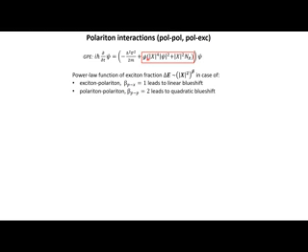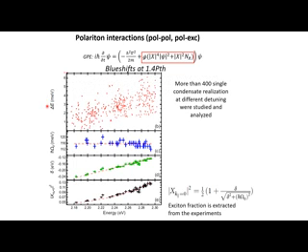So first we investigate polariton interaction. Is there any contribution from polariton scattering or polariton-exciton scattering that we know is present in the standard Gross-Pitaevskii equation for the polariton system? We experimentally studied how the blueshift for a single condensate realization changes with respect to the energy of the mode. And for the whole range, we measured reflectivity maps, and from the anti-crossing of the upper and lower polariton branches, we extracted the Rabi splitting between them, and also the detuning between cavity mode and exciton.